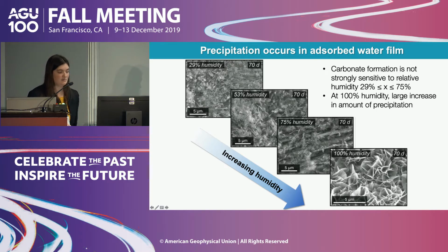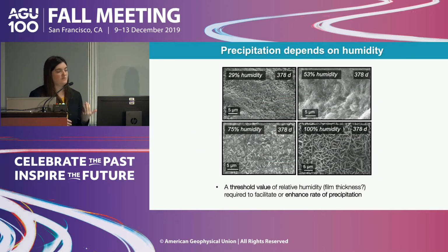In contrast, in our 100% humidity experiment, shown in the lower right, we observed these very large crystalline magnesium carbonate minerals forming that continue to grow throughout the experimental duration. So to summarize these observations, these are our brucite surfaces reacted with atmospheric CO2 for 378 days, which is the end of the experiment, where again we apparently have this threshold effect where at low humidity conditions we see little overall reaction, little difference between humidity, and little extensive continued carbonate growth. This suggests that we have a sort of threshold value of relative humidity, perhaps related to a threshold water film thickness that's required to facilitate more extensive reaction, potentially higher rates of reaction.